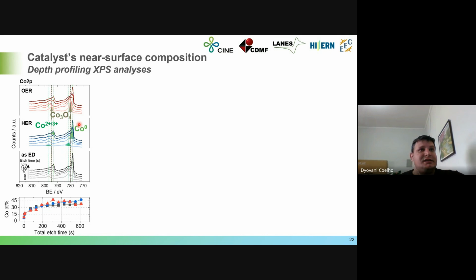But for oxygen evolution reaction, we can see the characteristic shift of these peaks and the behavior of high valence cobalt. These peaks are actually responsible for high cobalt valence, and this high cobalt valence is stable in alkaline media. So this explains why during the oxygen evolution reaction the cobalt concentration in the electrolyte is stable, it doesn't increase. As soon as this higher valence cobalt oxide is produced, the catalyst surface is passivated and protected. So there is no more catalyst dissolution, even with these steps of open circuit potential.